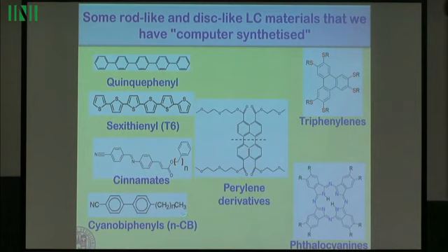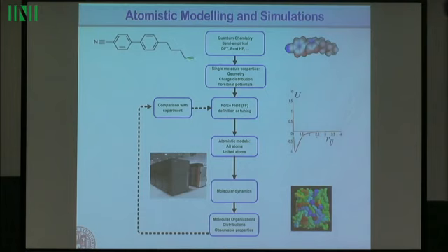So this we have done. And what is the synthesis? The synthesis means start from this chemical formula, do some quantum mechanics, quantum chemistry, which is now reasonably standard, using some DFT method or better, and then you get the geometry. This color here represents the partial charge on every atom, because even though the molecule is neutral, every atom has a different pulling strength with respect to the electron, a different electronegativity. So there is a different partial charge, and that is very important.